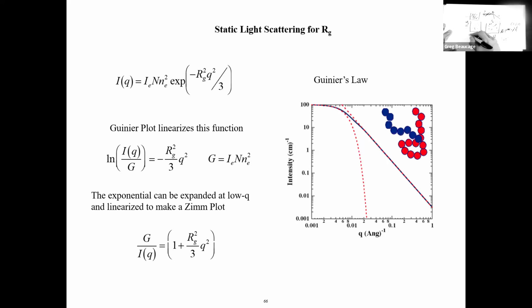So it's a function of pi in concentration, or in rho. Rho is concentration. If you want to know the change in pi with respect to concentration that's driving this, it's d pi d rho. In polymers, you have to divide by N, because it's mass, and there's mass by N. The number of dots is the mass in the system divided by N, the mass of one dot. So the molecular weight of the chain is in there. It's got to be 1 over N, plus this term.